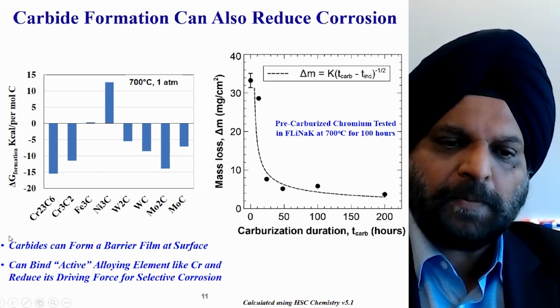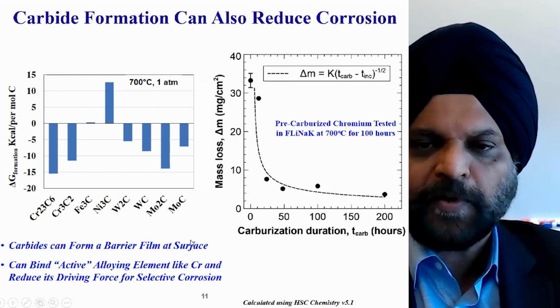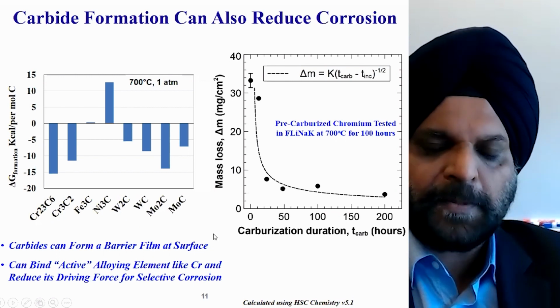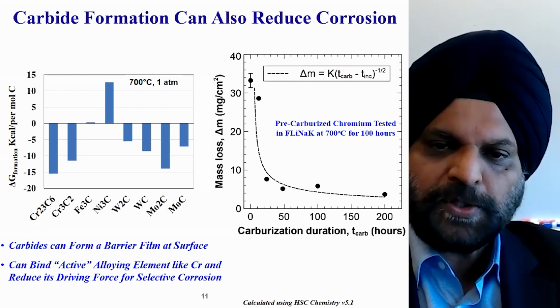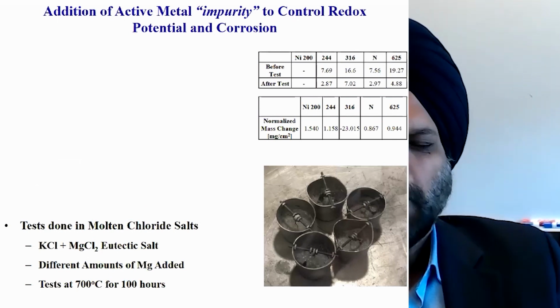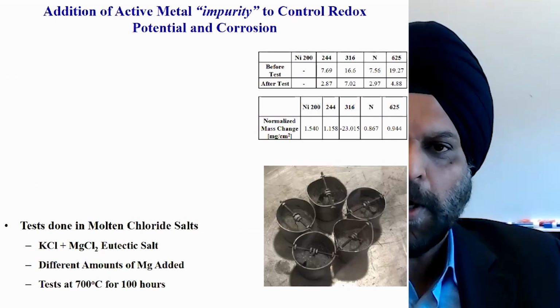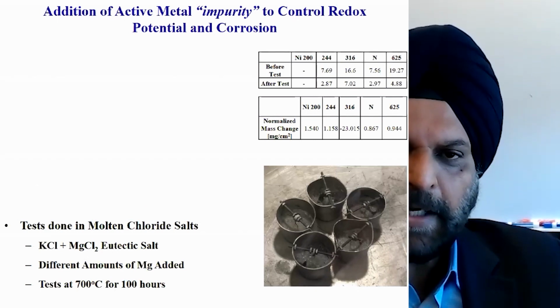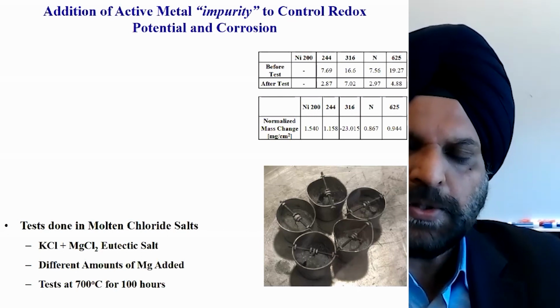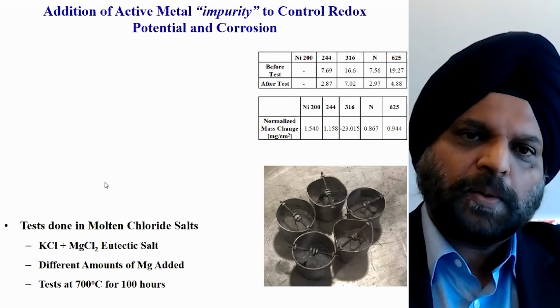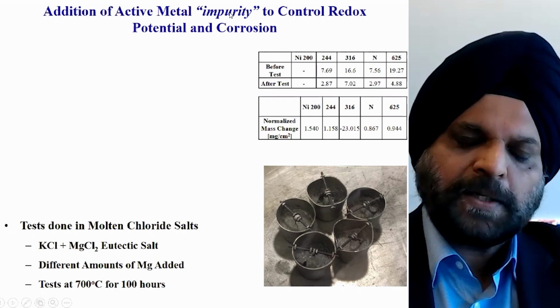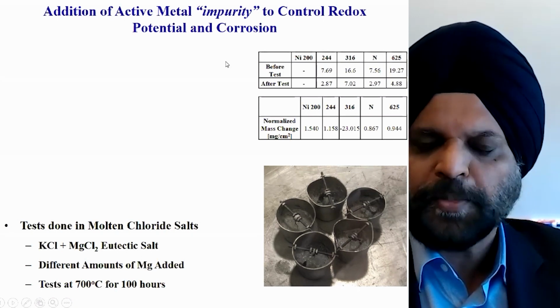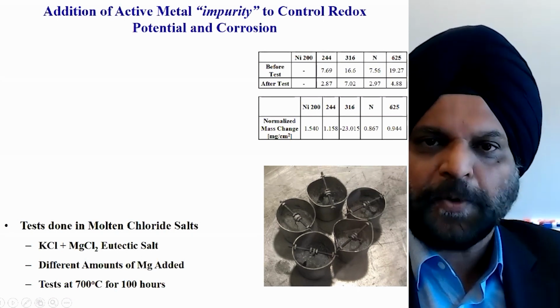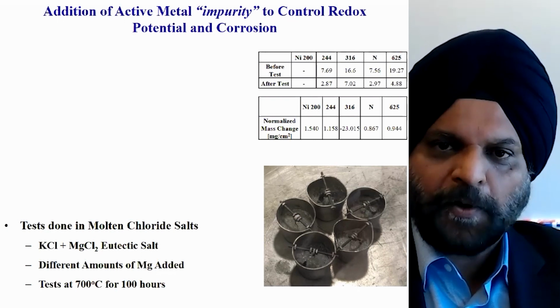But carbides can also form a barrier film, but for that you have to have a continuous film or an alloying element in large proportions. The last impurity that I want to talk about is the active metal that we add to control redox. Again, I'm calling it an impurity, but it can be a good impurity or a bad one, depending upon what we are looking for.